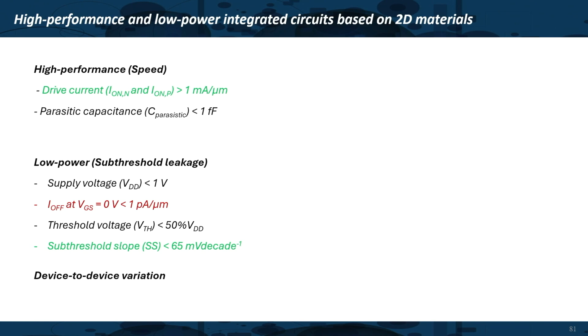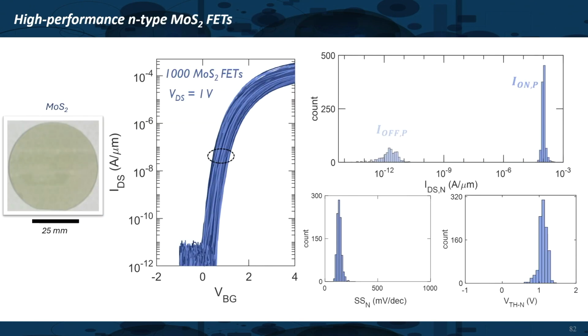So we have started looking into this. These are our most recent results on MoS2. I think right now there is a consensus that antimony is the best contact material for 2D materials. I mean, bismuth is also very good. Here we are using gold, and that's why we don't reach as high performance as milliamps per micrometer, but we get to consistently 300 microamps per micrometer on 1000 devices, right.